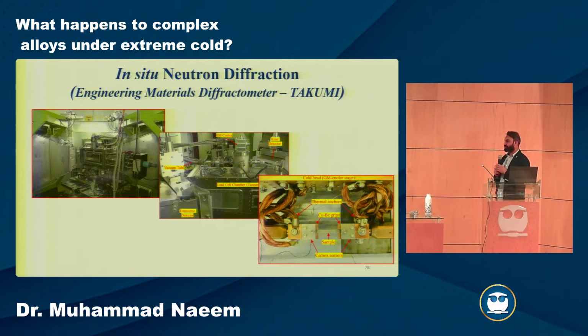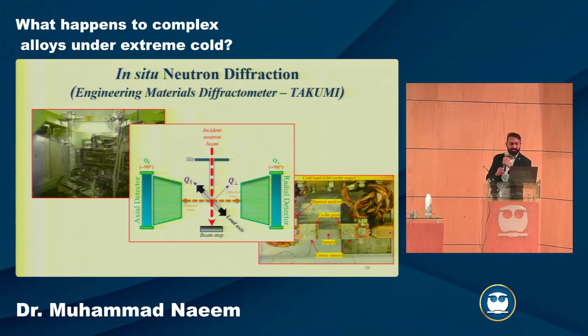And ultimately through conduction, we get around 15 Kelvin temperature on our sample. So 15 Kelvin is a very low temperature, right? There are a number of applications which do use such low temperatures, which I'll come to in a bit. So this is a very simple schematic of what's happening. As I mentioned, neutrons are coming from this side, the sample is over here, and the beam interacts with the sample, and it is affected depending on loading and transverse directions, and we get signals in our detectors.